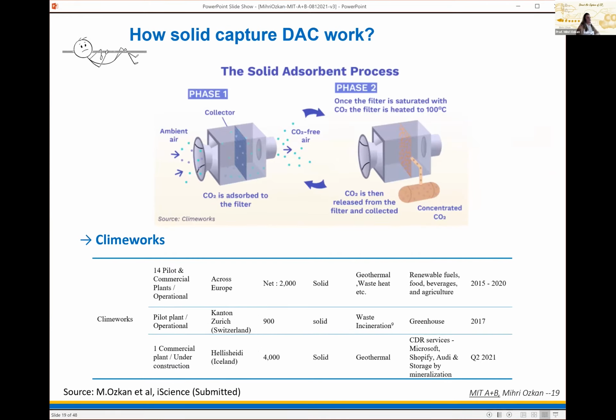The solid capture DAC uses a different technique where you have, let's say, membranes or filters that can capture and collect carbon dioxide. Once the carbon dioxide has accumulated and saturated in these filters, then by heating to 100 degrees C or so, we can collect and concentrate this carbon dioxide. Climeworks is the leading company on this. They have a number of pilot plants operational, about 14 or more. And they have another one in construction in Iceland, with around 4,000 ton per year capacity.